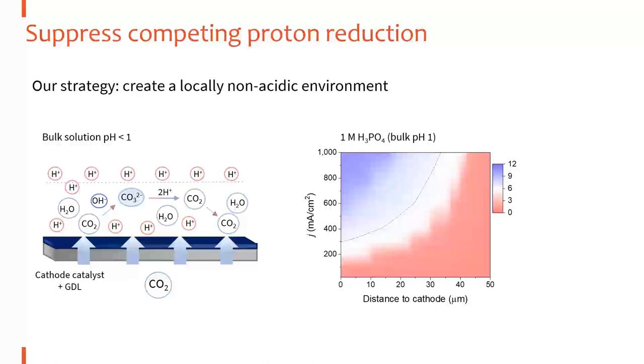So in this area, you can see the pH is higher, in blue color. This area is a sweet spot for our working condition, because here the local pH is higher than the pKa, while in the bulk condition, the pH is below the pKa. That means here we have a relatively alkaline condition, and here we have the acidic condition.